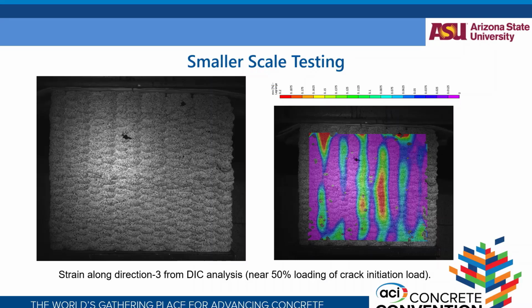This is the DIC image, taken around 50% of the cracking load, not even the peak load. When I say initial cracking load, it's when these joints cracked before even reaching higher loads. We can see a high stress concentration on the filament joints, which was expected, and we can see that through DIC.